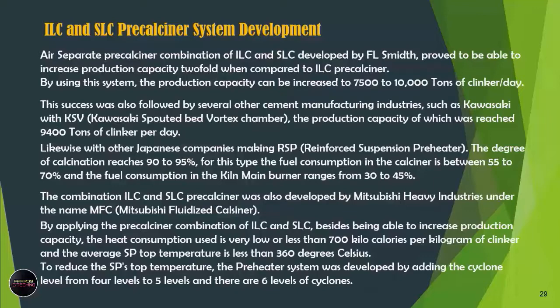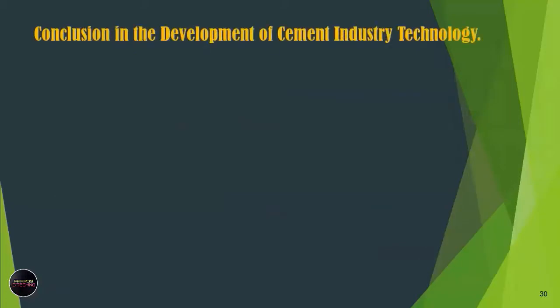By applying the precalciner combination of ILC and SLC, besides being able to increase production capacity, the heat consumption is very low, less than 700 kilocalories per kilogram of clinker, and the average SP top temperature is less than 360 degrees Celsius. To reduce the SP's top temperature, the preheater system was developed by adding the cyclone level from 4 levels to 5 levels, and there are even 6 levels of cyclones.